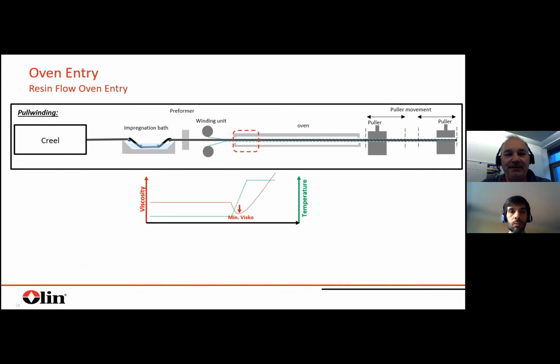So what it means, for sure, in everything before the oven, you have maybe some temperature which has an impact on the viscosity of your resin, kind of aging. But often it's a quite simple setup, just pulling it through, no real aging. But if you then go to the oven, here you have, for example, a viscosity of 600 millipascal second, but then you heat up the profile and the resin, which means the viscosity drops to some extent. And then the reaction kicks in and then viscosity is built up. But you created a viscosity minimum at the oven entry.